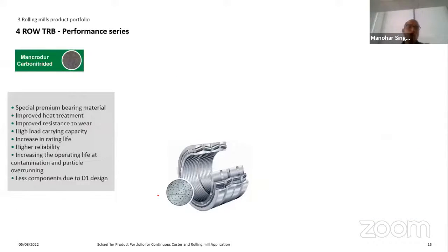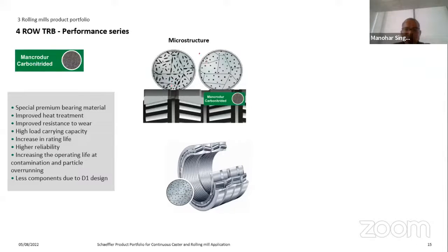First of all, in roll neck application, the raceway of the bearing should have high hardness so that it can protect the bearing from wear. At the same time, the surface of the bearing should be ductile so that due to contamination or the cycling of weared out particle from the bearing itself, it should not initiate the crack, and that crack should not propagate. So with this special material, we are getting something like this microstructure.